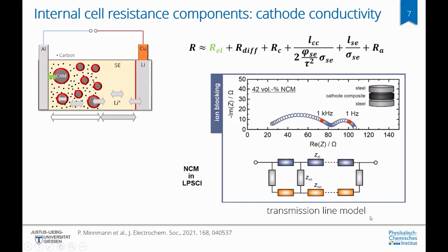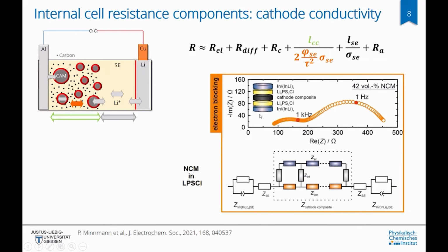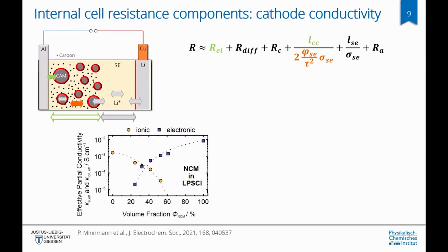And for this, he used a transmission line model to evaluate the conductivity. Similarly, he placed the cathode composite between two argyrodite pellets and then built a cell with indium-lithium electrodes in order to have an electron blocking cell, which means that only the ions transport through the cathode composite. And with this more complex transmission line model, Philipp Minnmann was able to evaluate only the ionic conductivity of the composite cathode. And this he brought together in this diagram, which summarizes the effective ionic and electronic partial conductivities of